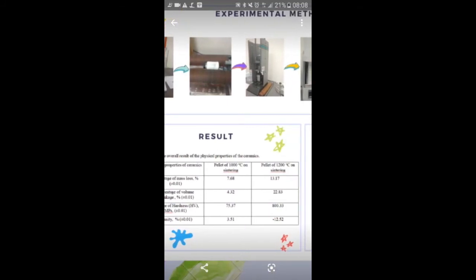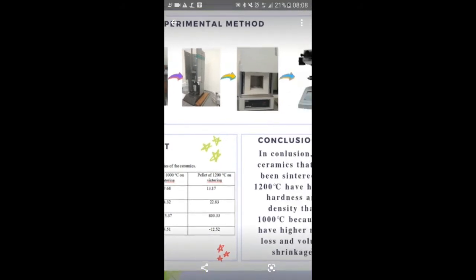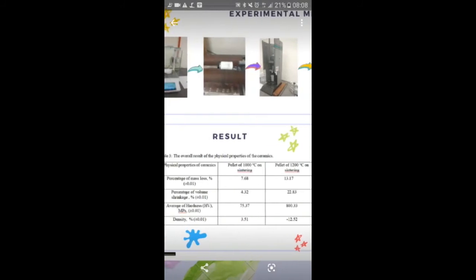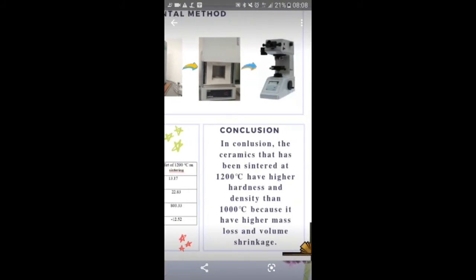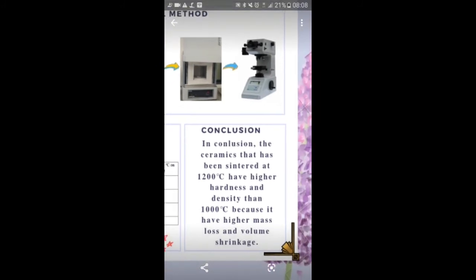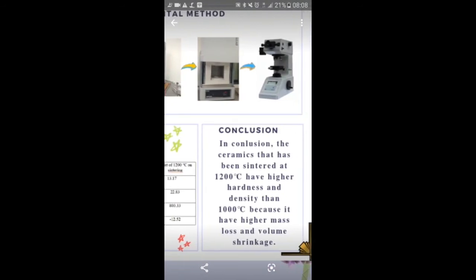Hence, the porosity of the ceramic is much smaller and more compact after sintering at 1200 degrees Celsius. The ceramic has a larger density because of the high percentage of mass loss and volume shrinkage, so the sample tends to be smaller but compact in shape. In conclusion, the ceramic sintered at 1200 degrees Celsius has a higher hardness and density compared to the 1000 degrees Celsius ceramic because it has a higher mass loss and volume shrinkage.